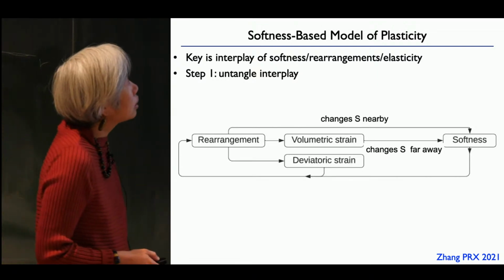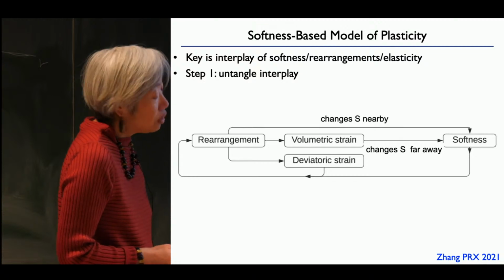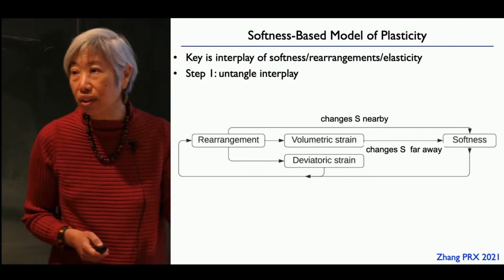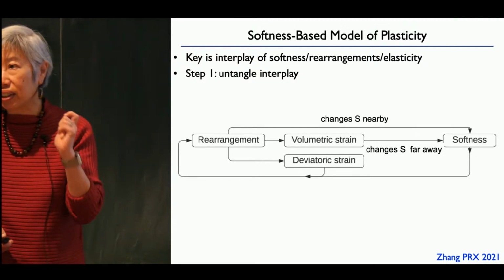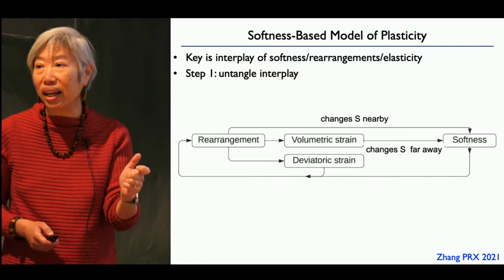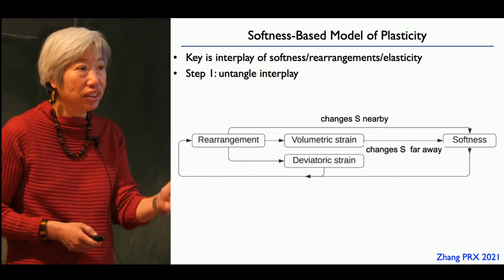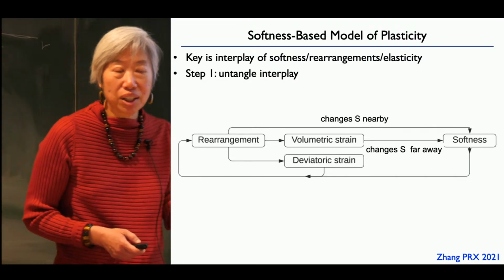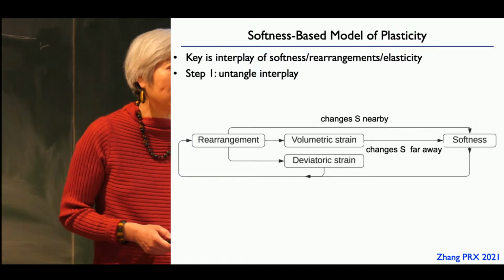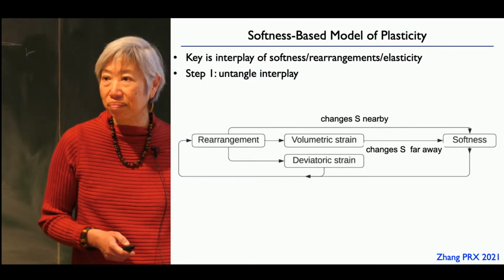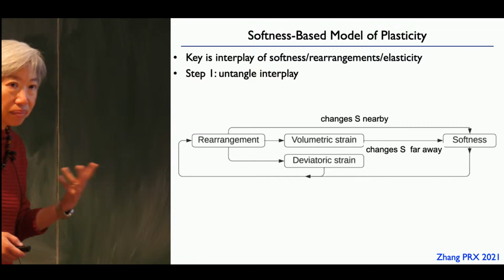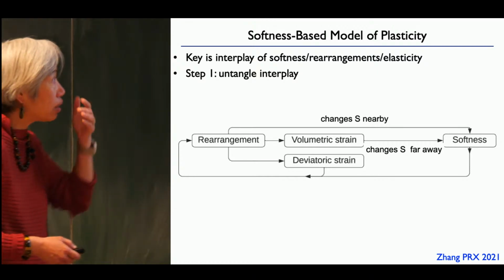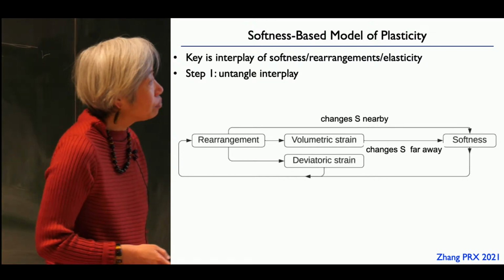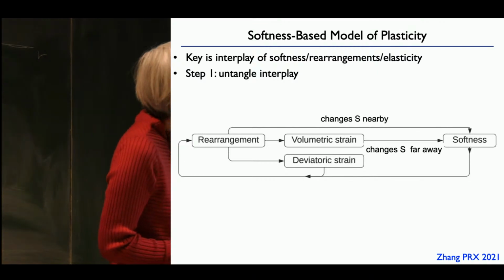So what do we do with this? I should say that it was only for the most brittle system, for Ludovic's system, that we used Y, the local structure predictor of yield stress. For the other two systems, we did use softness trained with support vector regression. And it turned out on delta squared min. Okay, and that turned out to work quite well for those systems.